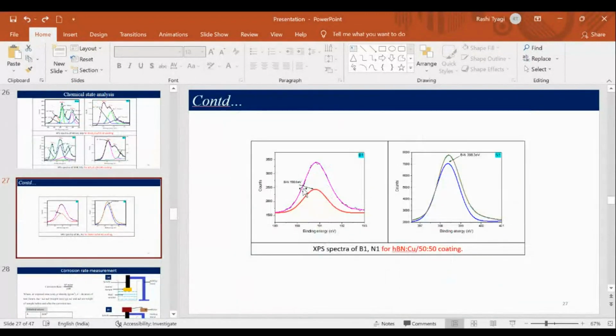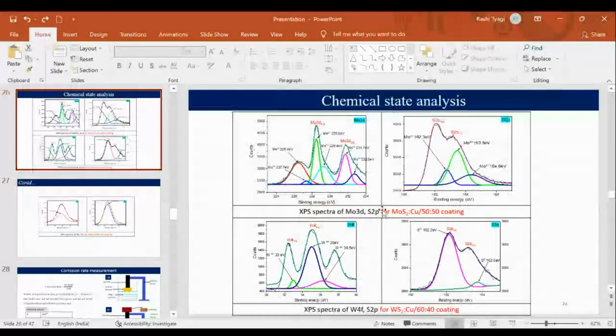Also, from the literature, we have found that the boron nitride peak is obtained at 190.8. So we can say that boron nitride is completely deposited. It is not dissociated or converted into a non-lubricating compound. Similarly, molybdenum is not dissociated but forms the MoS2 compound.